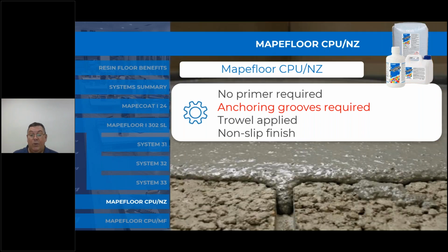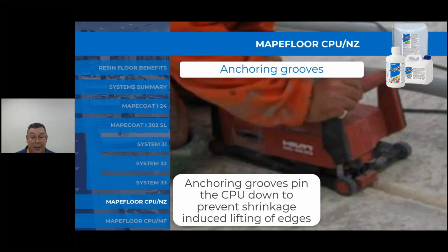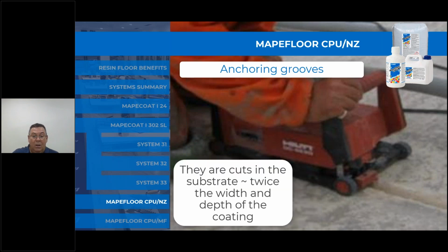This is just showing the anchoring grooves that are required. So when we talk about the anchoring grooves, they actually pin the cement polyurethane down to prevent any shrinkage or lifting up from the edges. It's an important criteria required by all cement polyurethane materials. The idea is to cut into the substrate twice the width and the depth of the actual coating that's being applied.